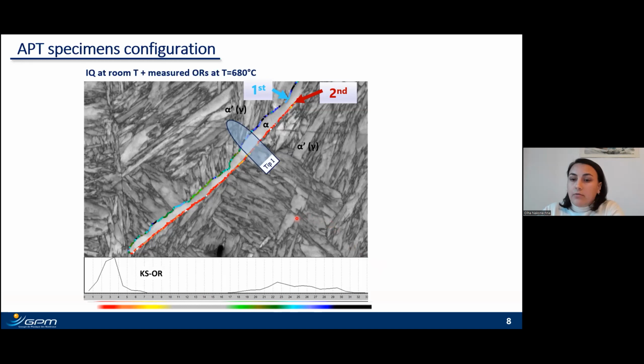Therefore, the first goal was to prepare the APT tip in a way that will contain both sides of the ferrite grain, as schematically shown on the slide. The next step was to prepare a set of APT tips like that, because first we wanted to increase the statistics of the obtained results, but also we were interested if we would obtain a reproducible result along the same ferrite grain, as we often observe different shape and thickness variation along the investigated ferrite grain.